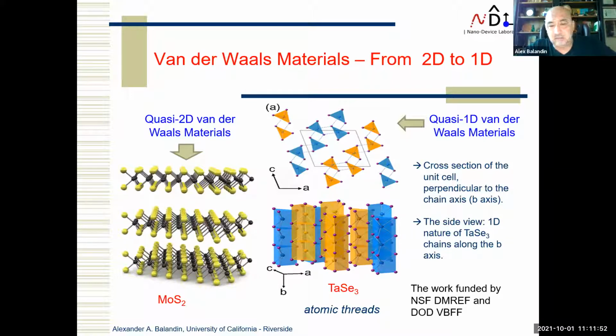And as I already mentioned, today most people talk about two-dimensional materials, but now I also have a very active research thrust on van der Waals materials which have a one-dimensional motif in their crystal structure. Just to explain the terminology, conventionally in the two-dimensional case, you have a layer which has strong covalent bonds. Then between the layers, you have weak van der Waals bonds. Of course, the first example is graphene, but then you have transition metal chalcogenides like MoS2, where you have a tri-layer with strong covalent bonds, and then you can exfoliate and you have a quasi two-dimensional material, right?